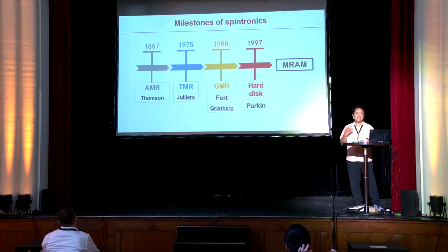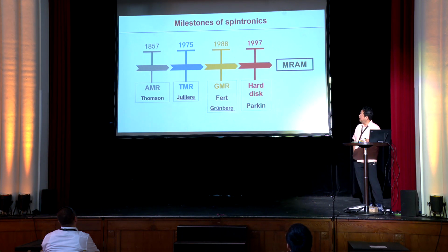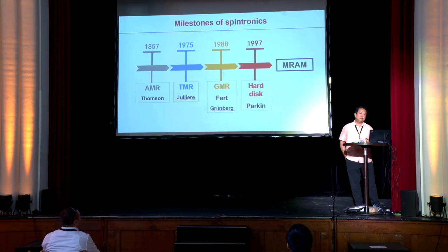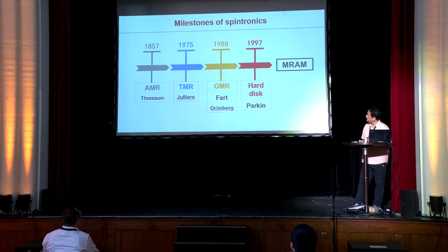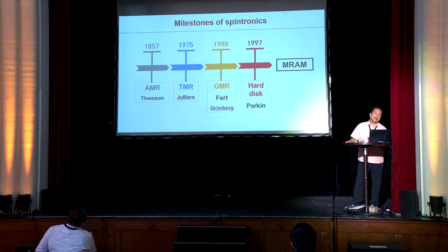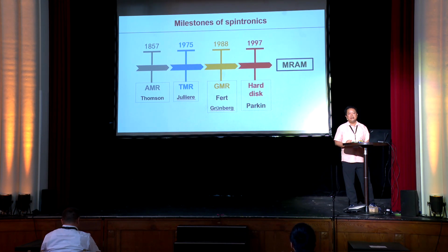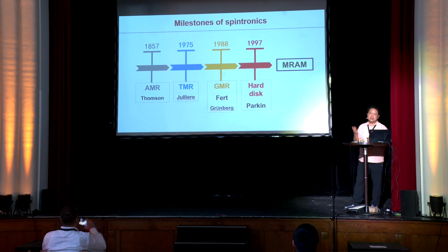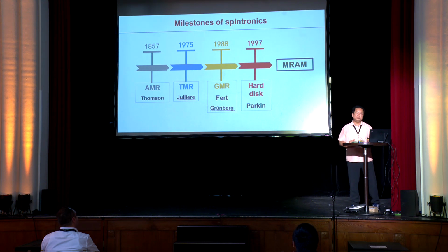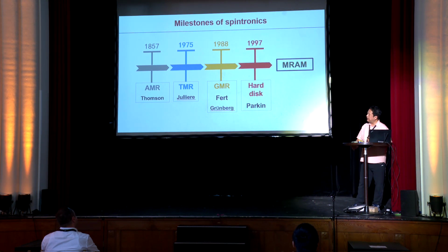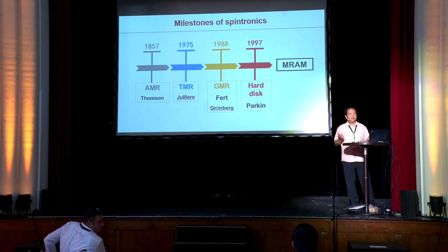In a broader sense, it all started a very long time ago, more than 100 years ago, in 1857, when Lord Kelvin wrote a letter to the Proceedings of the British Royal Society, talking about the observation of the AMR effect, the anisotropic magnetic resistance. Meaning that in 3D magnetic metals, the resistance depends on the angle between the field direction and the current direction. This was later understood as originating from spin orbit coupling, but the real understanding, from the spin polarized band structure point of view, has come only in very recent years, of how spin orbit coupling can induce the AMR effect. But before we understood the AMR, people had already been using it as a field sensor in many areas.